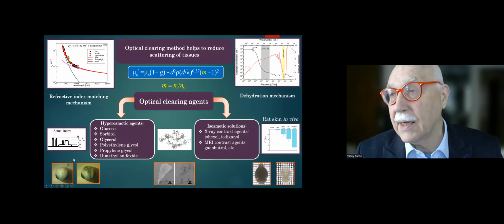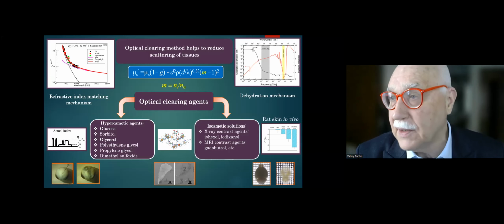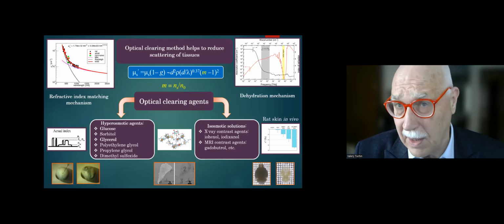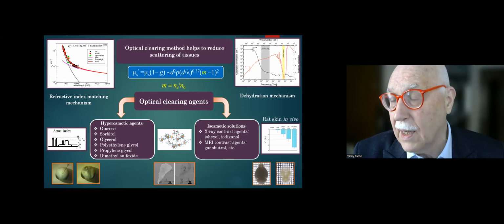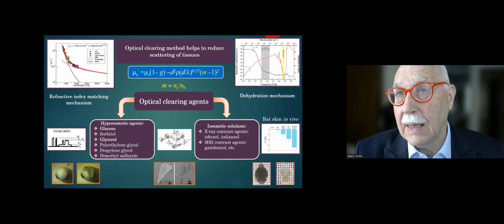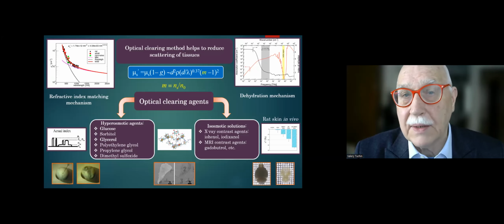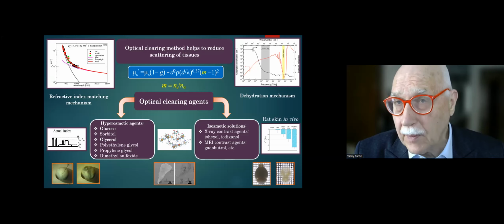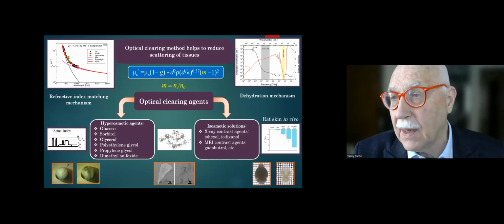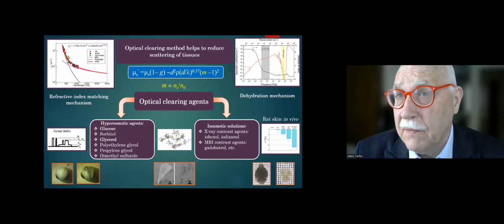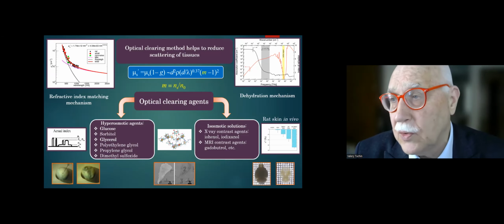In that case, we can get both reduction of water content, so absorption in the terahertz range, because this is a water absorption, the red curve. This is the water absorption, which is the main chromophore in tissue, because in soft tissue, it's up to 80% of water. Therefore, the penetration of light into tissue and also the blurring of the images depend on the water content in tissue, both due to refractive index mismatch and also due to absorption.